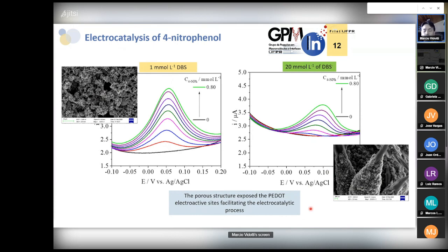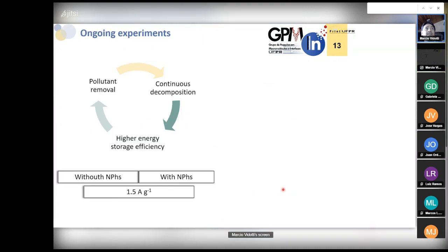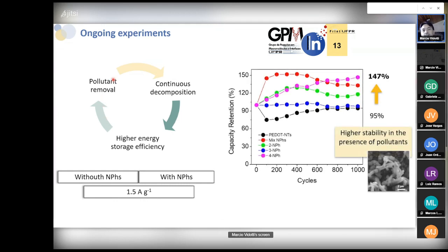So this was the work done in England with Bruna, but now we are trying to adapt this methodology to get, as I said before, the merge of electrocatalysis and energy storage. So we are planning at the same time to remove these pollutants and, under continuous cycling, to get higher energy under a very high current for the application. So if we compare, for example, the results I showed in the publication before, the capacitance or the charge transfer between the electrodes increased very highly compared with no presence of the pollutants, which indicates that in fact we are getting the energy or the electrons from these pollutants and really using this energy to do something more important.